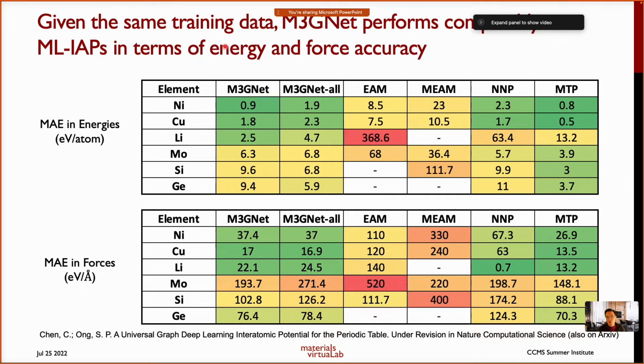Now, the first thing we did was to just test out the architecture itself. We used the same elemental training data as we did for our benchmark of the machine learning interatomic potentials, things like FCC nickel and copper, lithium and moly, silicon and germanium. What this plot shows is that given the same training data, our M3GNet architecture performs very comparably to the machine learning interatomic potentials that are already out there, and much better than your EAM and MEAM potentials, okay? So in other words, the architecture itself is not going to be a limitation in developing an interatomic potential, right?